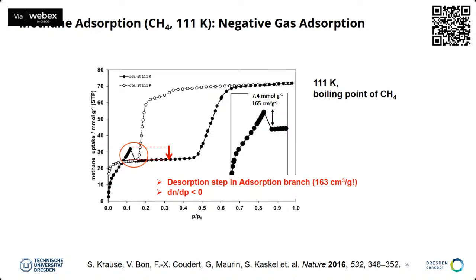And then for the first time, we saw a very strange adsorption isotherm. So this material takes up a huge amount of gas. We are here at 70 millimole per gram. But when you adsorb the gas, when you start to put some gas inside, here you see a very strange step. So there's a negative step in the adsorption isotherm. And then it's recovering. There's a big uptake again, and then there's a desorption step.